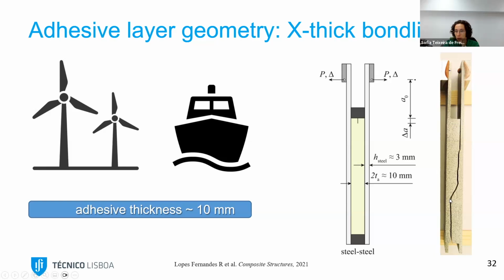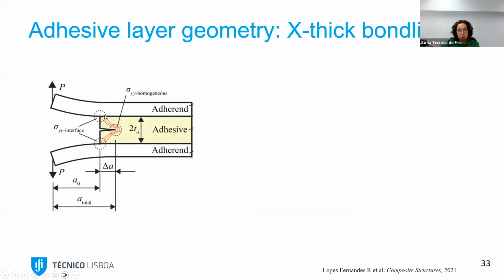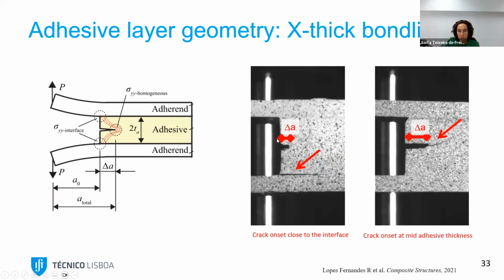And you see that the crack propagates in different regions within the adhesive. And this one propagated like that, but others propagated in a different way, in a different crack path. So by creating these very thick bond lines, normally we would only have 1 stress concentration, which would be here in the crack tip, 1 singularity. But by creating these thick bond lines, we create two extra singularities. So this region here and this region here also have stress concentrations because they have different materials and due to the geometry. So what we saw is that for a certain delta A, which was the initial crack length, sometimes we had a crack onset close to the interface. Sometimes we had a crack onset at the middle of the adhesive thickness. So it means that at certain points, sometimes this was predominant, and at other times this was predominant.